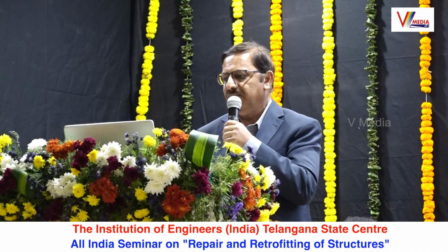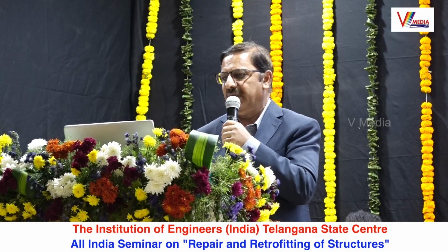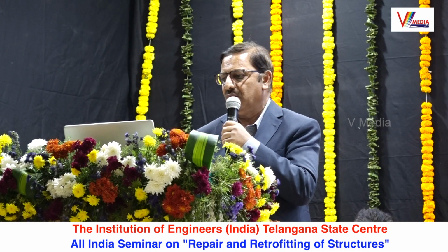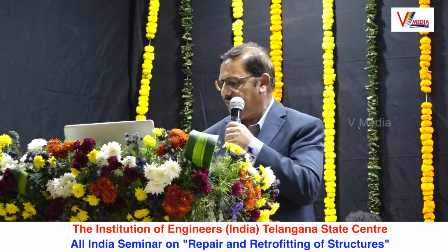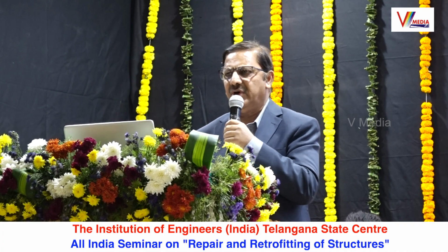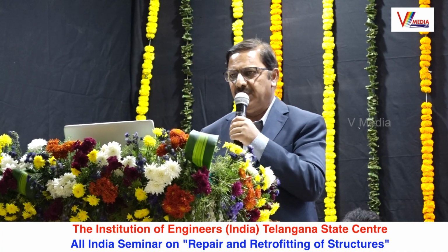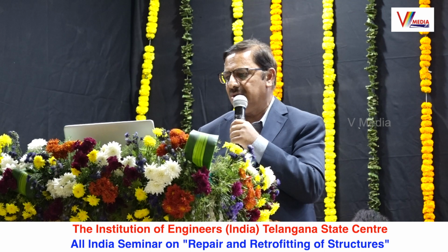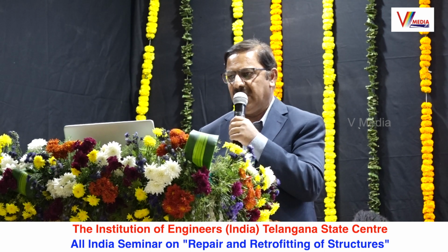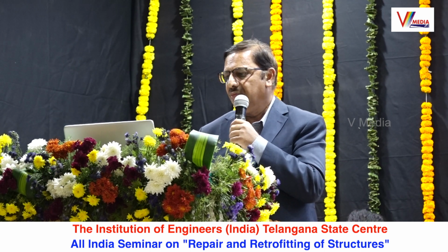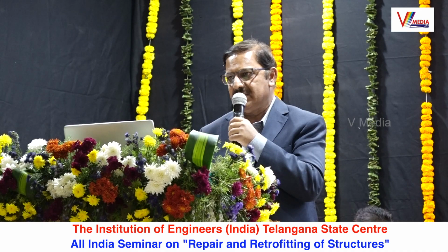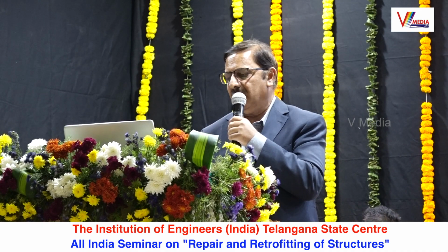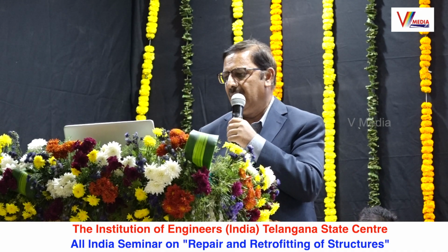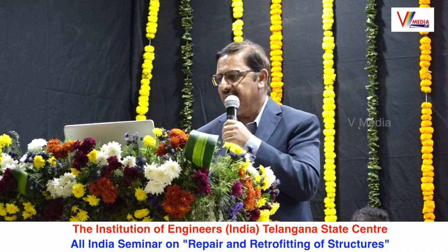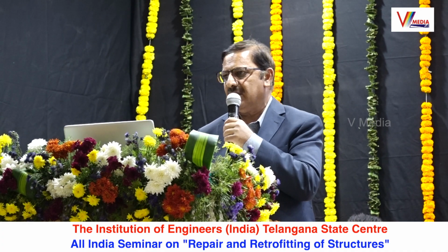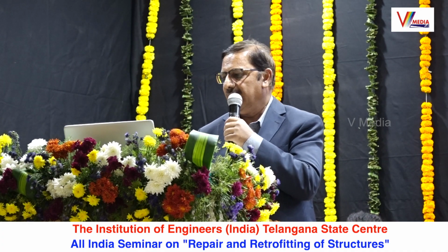The design life is claimed to be around 20 years based on a current density of 0.4 to 1.6. The operating current density for cathodic protection is somewhere between 1 and 2 milliampere per square meter. So I just calculated based on 1 milliampere per square meter, which is an average operating current. 40 grams will give you around 3.5 years. 160 grams, there are varying weights available, will give around 13 years. And if you use the highest weight, which is 330 grams, it will give you 28 years.